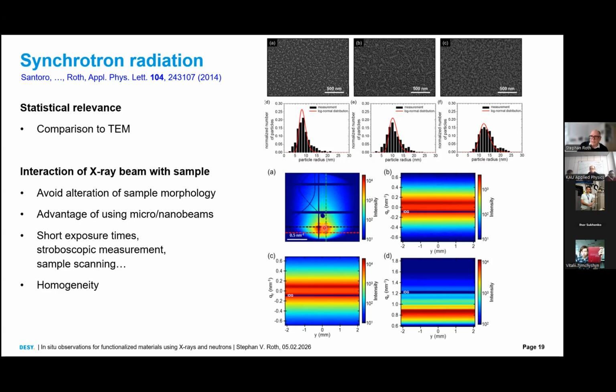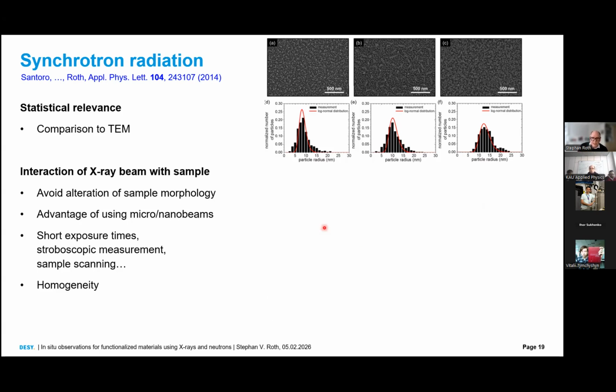The ultimate comparison is, of course, when you make an experiment with X-ray beams and then repeat the experiment without any X-rays, you take the two samples and compare them under an SEM or AFM. We do this regularly and we don't see any difference. So we know that our avoidance of radiation damage really works. But it's a very important question. Typically when you make proposals for scattering, you must write a sentence in there on how to avoid radiation damage, and this is what we did here.